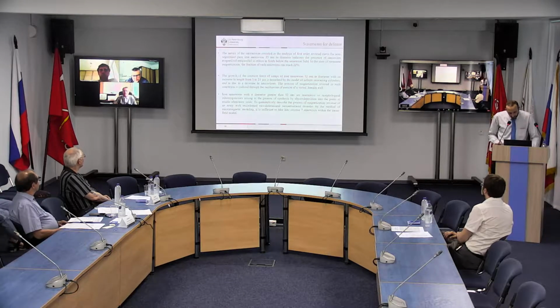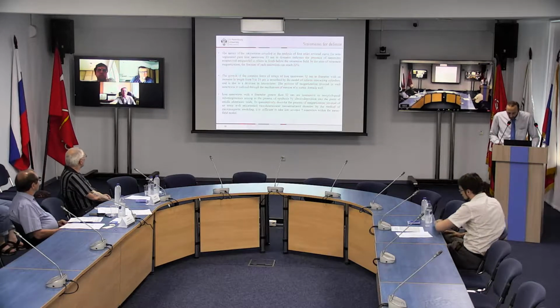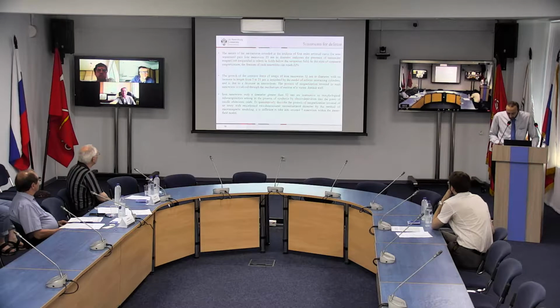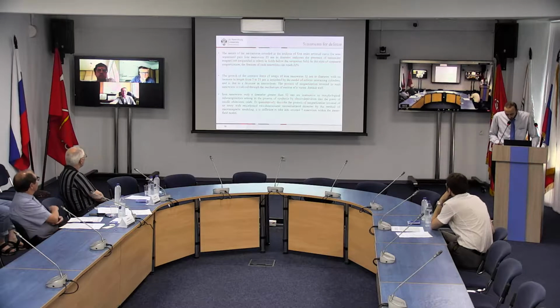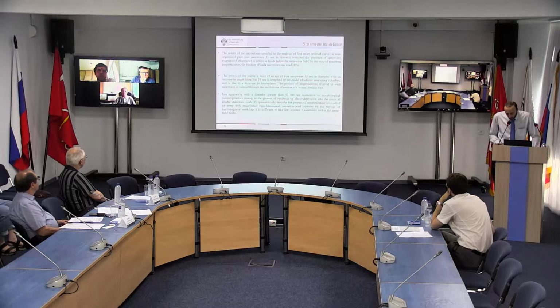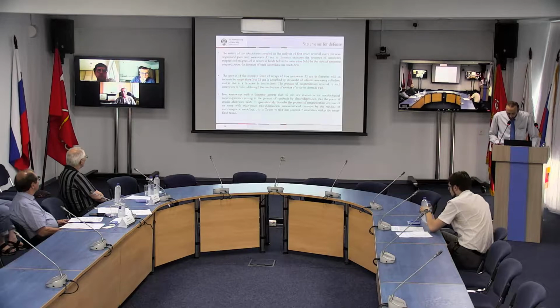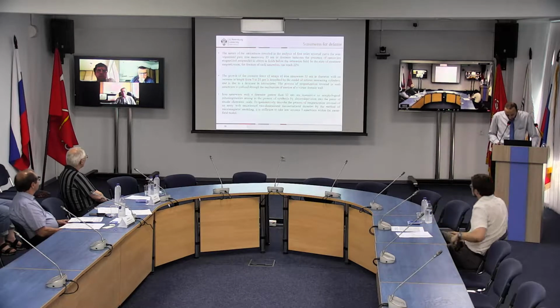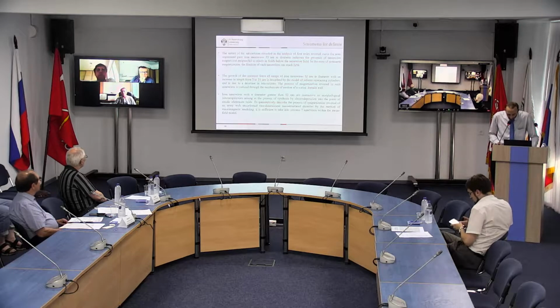Statements for defense. First point: the nature of interaction revealed in the analysis of first order reversal curves for FORC analysis for non-segmented pure iron nanowires 33 nanometers in diameter indicates the presence of nanowires magnetized antiparallel to others in a field below saturation field at remanence, in the state of remanent magnetization. The fraction of such nanowires is estimated roughly to be 22%.